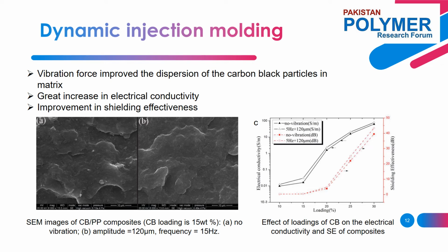Figure B shows a micrograph of the carbon black and polypropylene nanocomposite with the application of vibration force. It can be seen that the dispersion of carbon black particles in the matrix has improved significantly. The average particle size of carbon black decreased greatly because the blending of the melt was enhanced. The vibration force has a direct influence on the internal structure and microstructure of the products. The polymer is compressed and released periodically with different vibration amplitudes and frequencies under the effect of vibration force. It is beneficial to the dispersion of particles and the formation of a conducting network structure.